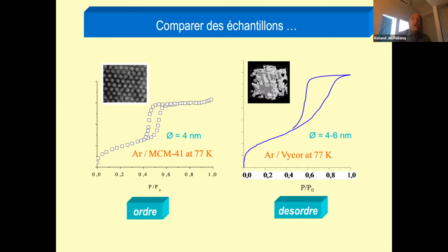So what's the influence of disorder on pore connectivity? Here I compare the adsorption isotherm of argon at 77K in MCM41 and Vycor—these are experimental data. For MCM41, we have this very vertical hysteresis loop, whereas when we move to the disordered system, we have a gradual filling up and a sharper desorption line.